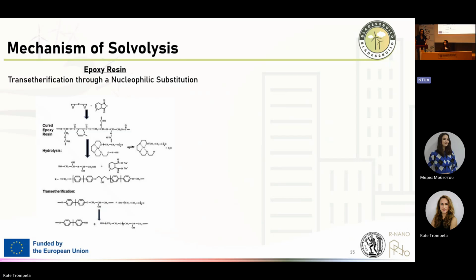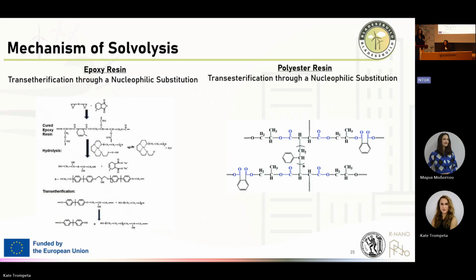So the mechanism of solvolysis with the epoxy resin, we have to see how the epoxy is produced. As Kate said, epoxies are connected through ether bonds. So the recycling comes through a transetherification through a nucleophilic substitution. And then the polyester resin, it says already in the name, we have ester bonds. So we have a transesterification mechanism through again a nucleophilic substitution. So in both epoxy and polyester there are electrophilic centers that are being attacked in the solvolysis by our nucleophilic either solvent or catalyst.